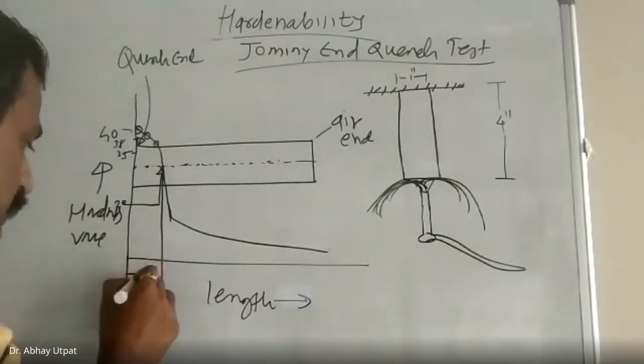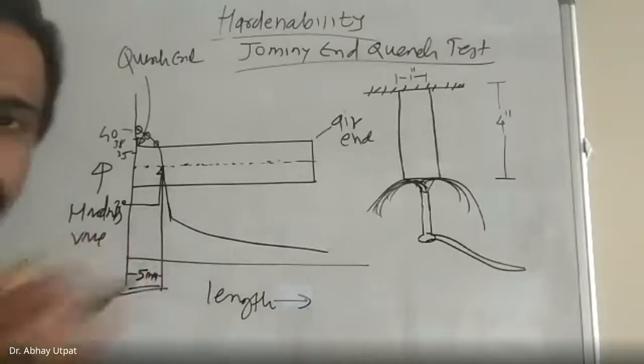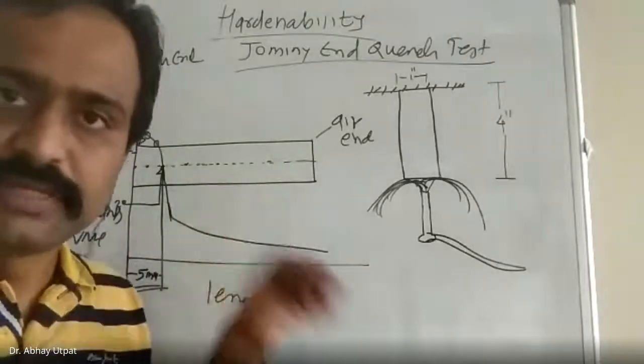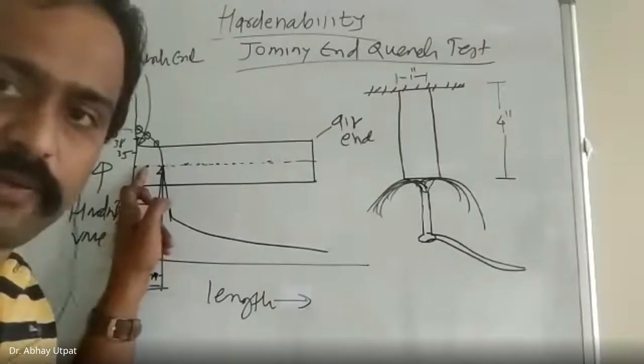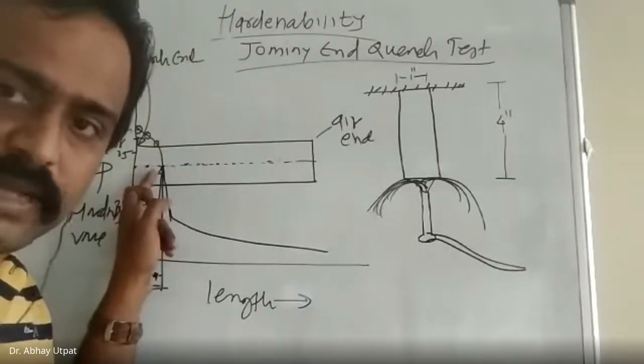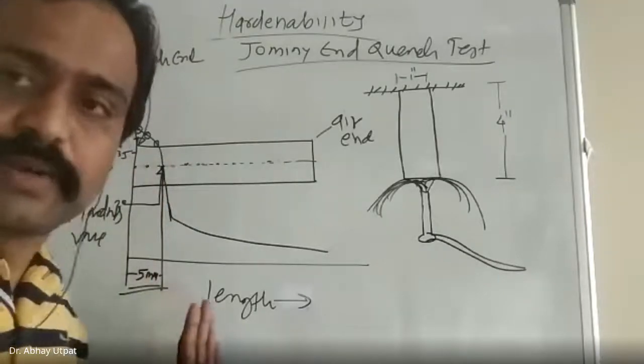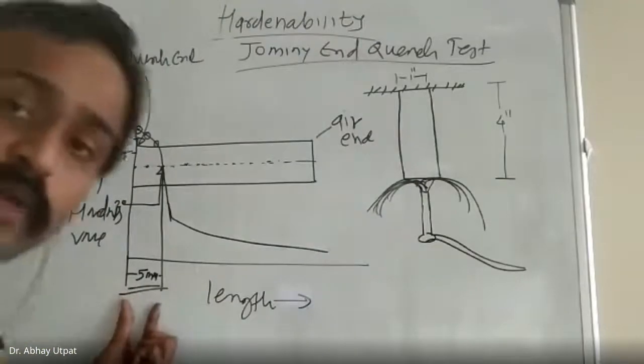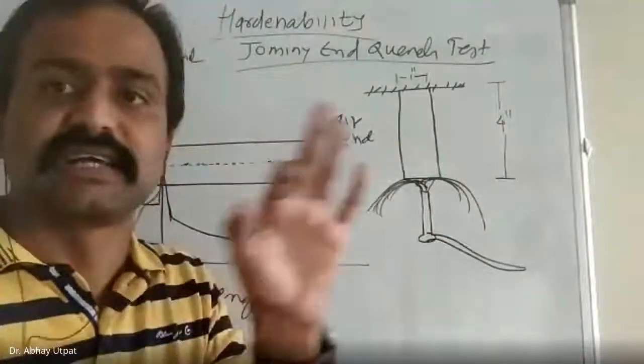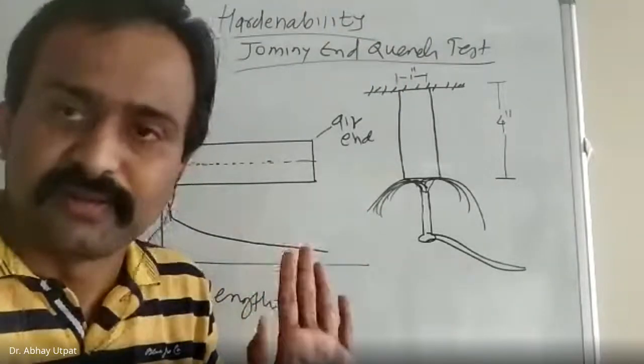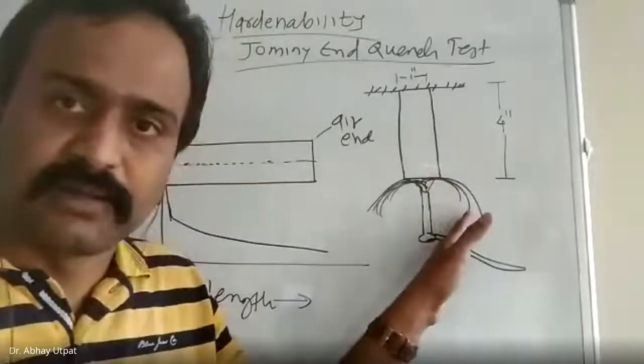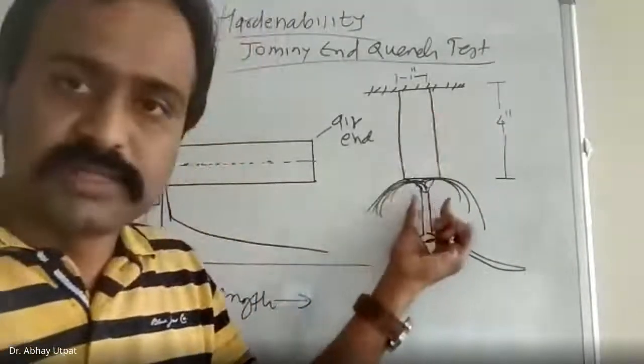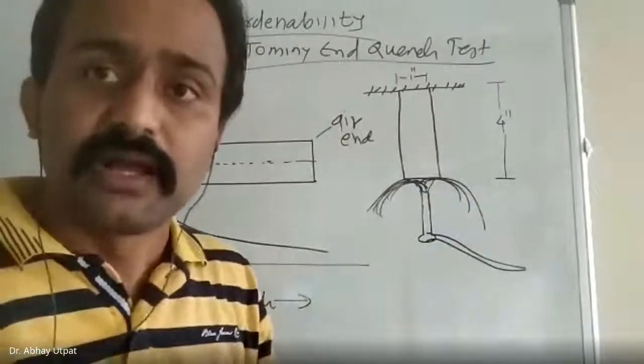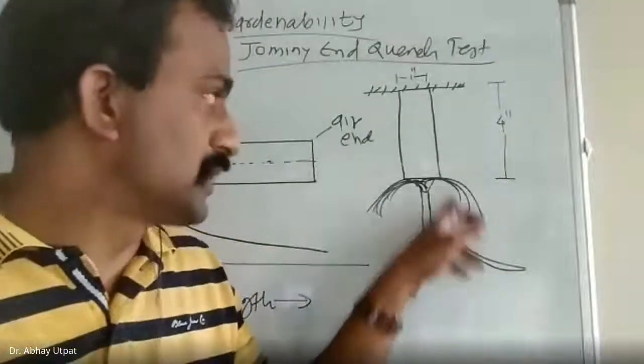Suppose this distance is 5 mm. Means at the end, hardness martensite is 100%. 1 mm 95, 2 mm 95, 3 mm 90, 4 mm 89, and 5 mm directly 20% martensite. Means sudden drop in hardness. So up to 5 mm quenchant has made effect. This is the concluding remark of the Jominy. What Jominy said: when you carry out this experiment, when you heat in the austenitic zone and end quench, this quenchant can make effect up to 5 mm length if you use this quenchant and this material.